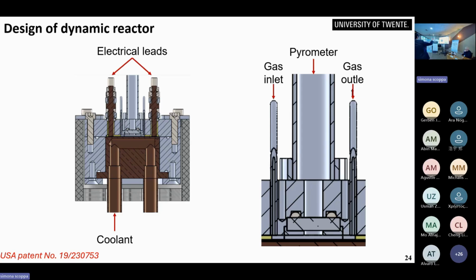So for that, we came up with this design that you see here, where we have essentially two electrical leads in contact with the material underneath. This is a reaction chamber where the gases come in from one side of the reactor and then exit. Inside this volume, we have a graphitic material where heat is generated by flowing a current. At the surface of this graphitic material, we have a nickel catalyst that activates the ammonia. This reactor design helps you provide heat very, very fast.